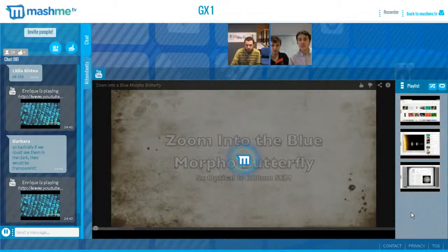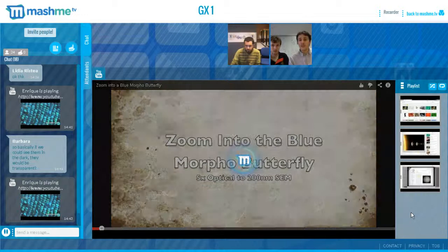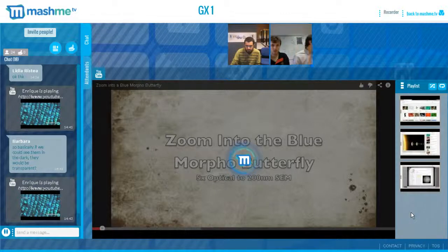The way to test whether they have structural colors is to put a drop of ethanol, so alcohol, or also water onto them, but ethanol is better because it wets the structure. As soon as the ethanol infiltrates these structures, you lose the contrast between the air and the chitin. So the refractive index contrast is lost, and then the butterfly wing scales suddenly become transparent. So it's really about nanostructure, whether it's dark or bright. It's about having this contrast between the two materials. As soon as you squeeze the structure together and lose the structure, you also lose the color. So I think that's a good way to explain it.